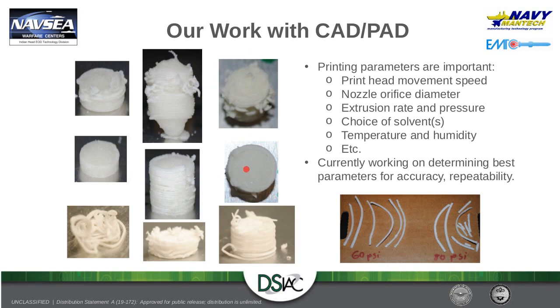Right now, Jorge is highlighting a couple of the better results that we found. While they seem okay, they have a couple of flaws that are somewhat problematic. In the center one, you can see a lot of delamination between the layers, and a sort of missing material on the side. Some of these other ones came out rather nicely, but they could not be repeated very easily. We tried the same settings again, and we weren't able to get a similar looking grain. Yes, and some of these also were printed with the smaller size nozzle, lending to the very short grain heights. But that's something that I'll elaborate on in the next slide.